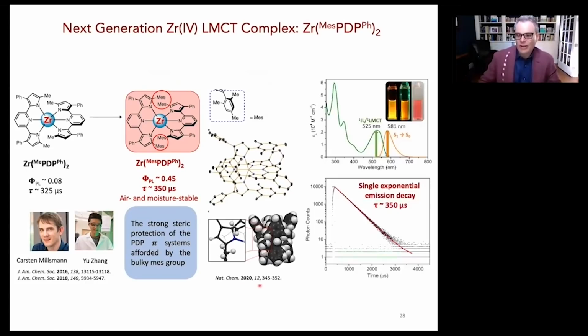And again, quantum yield of photoluminescence from this is 45%, but it has like a 350 microsecond lifetime. But it's the only zirconium compound I've ever seen that's air and moisture stable. So we can make these upconversion solutions on the benchtop and work with this on the benchtop. So we published this in 2020, but what was fascinating was they got a single exponential emission decay, and they originally had this assigned as singlet fluorescence, but singlet fluorescence doesn't really jive with that 350 microsecond lifetime.